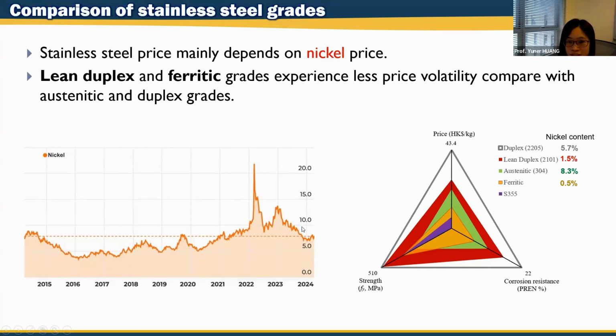So when the nickel price fluctuates a lot, duplex and austenitic will be influenced a lot, while for lean duplex and ferritic, the price is relatively stable. This is quite important when we are considering the construction cost, because by the time we are designing for stainless steel, if we choose austenitic, maybe we choose it when the nickel price is low. But when we start constructing, when we start buying and using the stainless steel, the nickel price becomes higher, then our construction project cost will be much higher. So there is an uncertainty if we use duplex and austenitic, because of the uncertainty of the nickel price. In comparison, if we choose lean duplex and ferritic, the price will be much more stable.